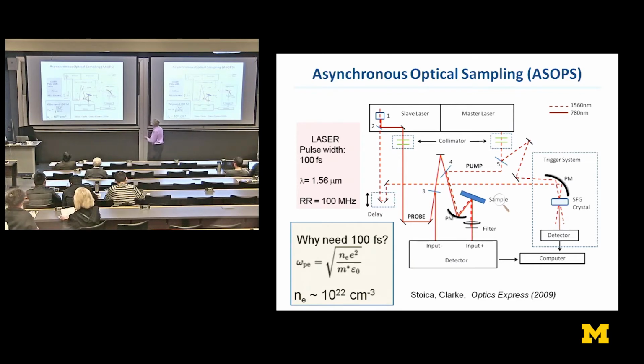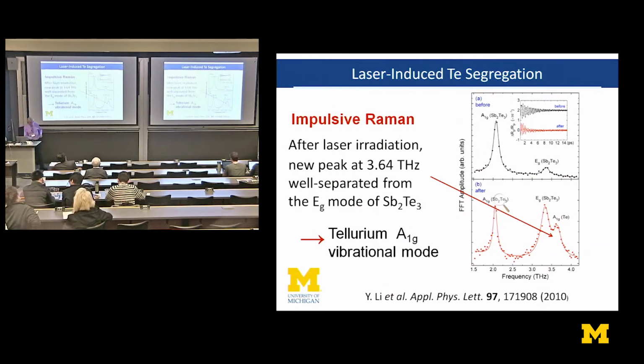So we published this. This is the first time that this kind of measurement had been done with fiber lasers, and we published this about 2009. One of the things we learned from doing measurements during the processing with the laser is that we indeed could modify an interatomic potential in this material, antimony telluride, by illuminating it with pulses from such a laser. And that was shown to us by this additional peak here.